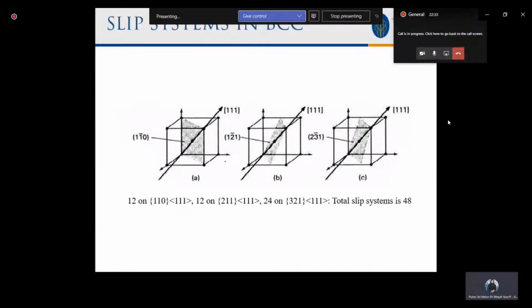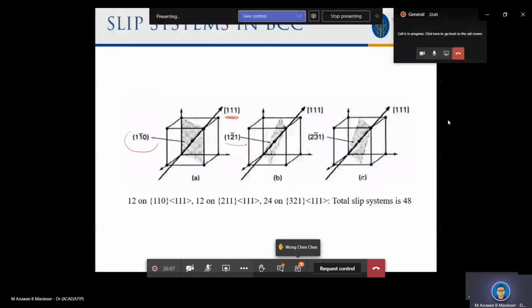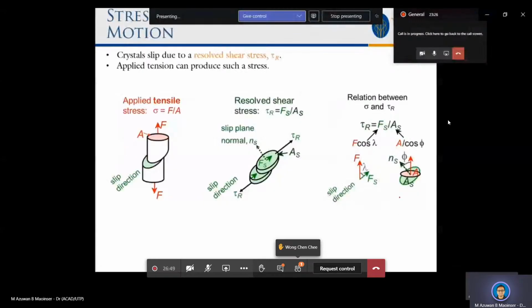Similarly for BCC, you can convince yourself that here, in the (1,-1,0) plane, you have direction <111>. Here you have plane (1,-2,1) with also direction <111>. Normally in BCC, the highest density direction is <111>. That is already known, so that one is not changing. Only the most packed crystalline planar density is changing. When you count this, 12, 12, and 24, you get 48. You can try to check whether what I say is correct, but I'm telling you it's 48. All right, that's all at the moment.